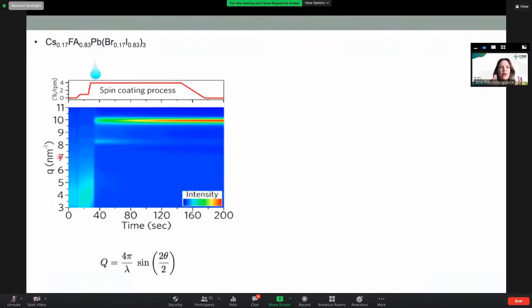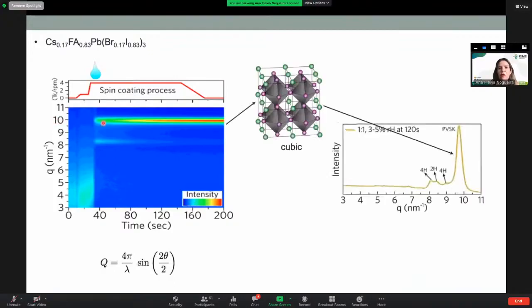And again, you can only obtain this kind of result if you go to the synchrotron, because you have a really fast acquisition of the X-ray spectrum. With this really fast acquisition, you can plot, for instance, the evolution of the diffraction peaks with time. So what do we have here in this result? Initially, just when I switch on the spin coater, we have this blurry signal from the precursors. And as soon as we drop the solvent, you see the formation of a very intense peak here at Q equal to 10. This peak corresponds to the cubic perovskite.